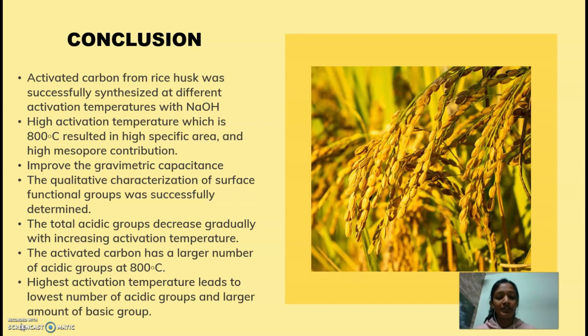This improved the gravimetric capacitance of the activated carbon when used as active material in a supercapacitor. The qualitative characterization of surface functional groups was successfully determined. The total acidic groups decreased gradually with increasing activation temperature. The acidic groups of carboxylic, lactonic, and phenolic decomposed at 100 to 650 degrees Celsius, which is lower than that of basic groups of quinone and carbonyl at 650 to 980 degrees Celsius.